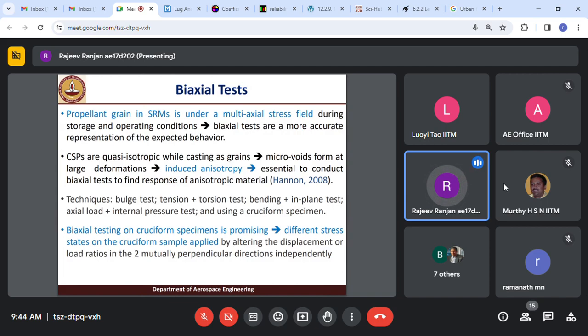In the literature, there are various techniques to do the biaxial test, like the bulge test, combining tension and torsion, combining bending and in-plane loading, as well as combining axial load and internal pressure, or using cruciform specimens. Out of these techniques, biaxial testing on a cruciform specimen is more promising, because here different stress on the sample can be obtained by altering the displacement or load ratios in two mutually perpendicular directions.